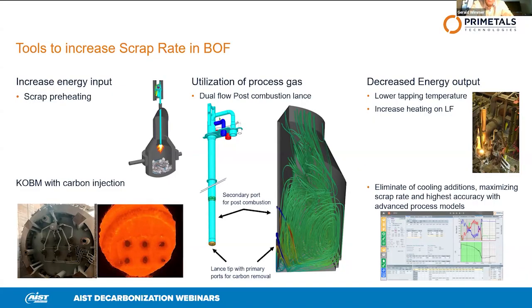This is best done by having accurate logistics and accurate process control. And for this, it turned out that process models are very helpful. So the process model allows upfront to calculate the heat with the accurate energy balance. Then we know precisely how much energy is available and how much scrap we can process with this energy. And then we can order the right amount of scrap and charge the maximum scrap amount possible. All in all, these tools allow for a standard BOF converter to increase the scrap rates to some 25%.